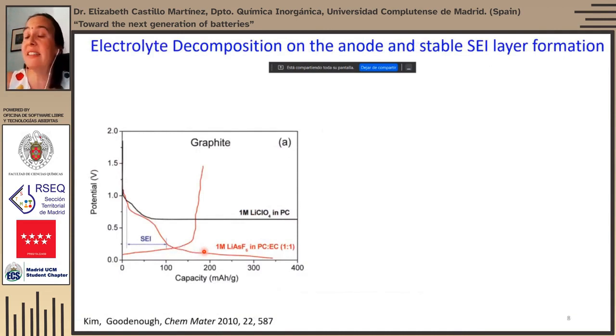But the development of these batteries had other issues to be solved. We said that these batteries had an electrolyte in which ions move. And for lithium-ion batteries, this electrolyte is composed of a lithium salt, lithium perchlorate, or lithium hexafluoroarsenate, or lithium hexafluorophosphate, the most common case, in a mixture of carbonate solvents, such as propylene carbonate or ethylene carbonate. What you can see here is that this electrolyte is thermodynamically unstable at the very low voltages at which lithium is intercalated into graphite, and therefore there is a continuous decomposition of the electrolyte.